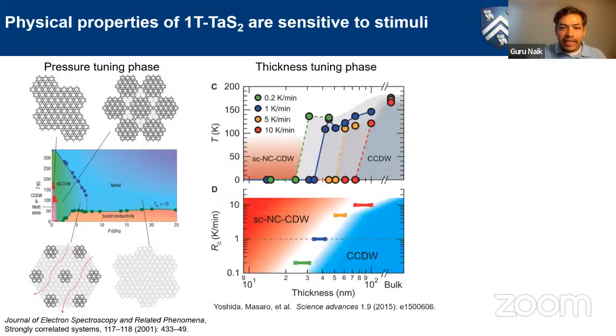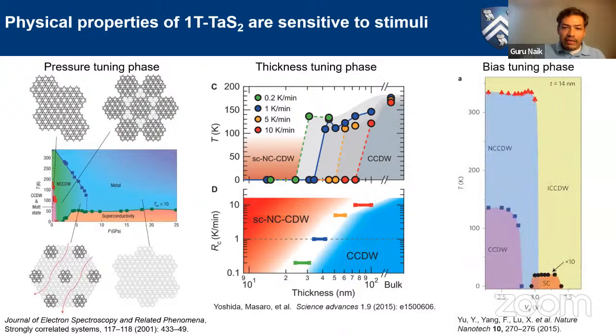And similarly, just by changing thickness, it's been shown you can again bring superconductivity or suppress charge ordering. And similarly, electrical bias, even a vertical field effect bias like a gate bias, or even in-plane electrical bias, both have been shown to tune the electronic properties of this material. So the question that we had was, what about optical properties? And we couldn't really find any material that talks about dielectric constants. There were many which used high intensity lasers and, for example, time domain reflectivity measurements, but none of them really talked about how the linear response function depends on any of these phases that exist in tantalum disulfide. So we wanted to try that.